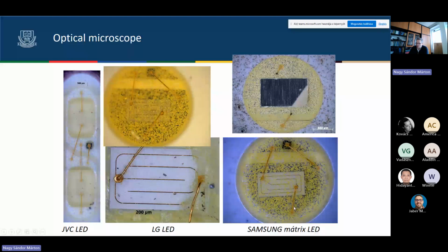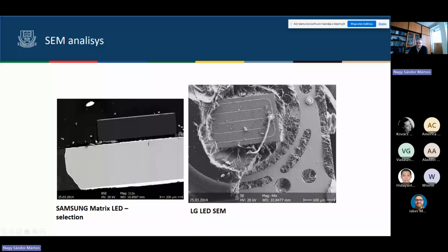The problem is that the amount is very small. One piece of LED has a very small mass and size. And here you can see the pure gold wires and the LED chip itself. We removed this layer a little bit, and you can see here the sapphire structure. And maybe you can see here the different layers. Maybe some slight difference in the colors can be seen on this picture. In the scanning electron microscopy, you can see the LED chip here. It's a sapphire structure, and this 4 micrometer layer on it contains the interesting and valuable materials. And here the wire can be seen.